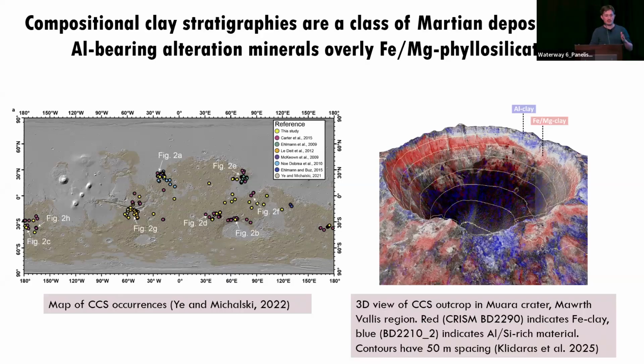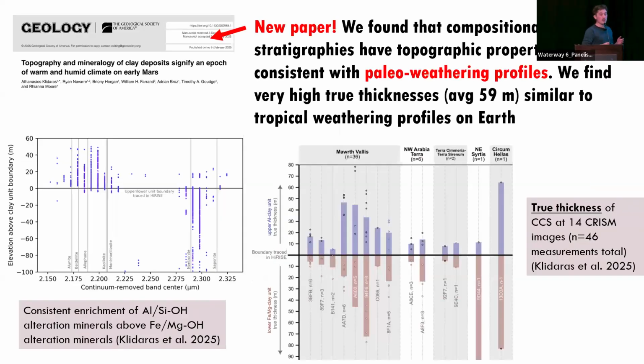They're typically restricted to mid-late Noachian terrain, but there is some spread into some younger Hesperian units. And here's a 3D visualization using CRISM data to highlight the different kinds of alteration minerals you get. So in blue, we see the aluminum-bearing alteration minerals, and in red, the iron-magnesium-bearing clays. We actually have a new paper that just came out in Geology a couple of weeks ago regarding these deposits.